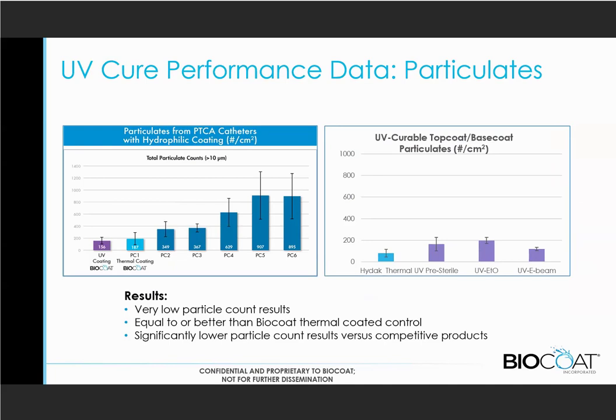The other part of that, of course, is the particulates. And what does that look like? Again, the interesting thing is that even though the lubricity data on those various angioplasty catheters looked pretty good, the particulate data tells a slightly different story. There were, again, two different groups: one with lower particulates, and one with higher variability of particulates. Here I'm presenting the number of particles per surface area, per centimeter squared, instead of total particles per device. You can see that our thermal coating matched up nicely with what we had with the neurovascular. The UV coating also has a very comparable amount of particles being generated on the low end.